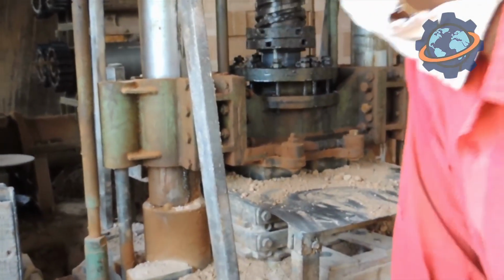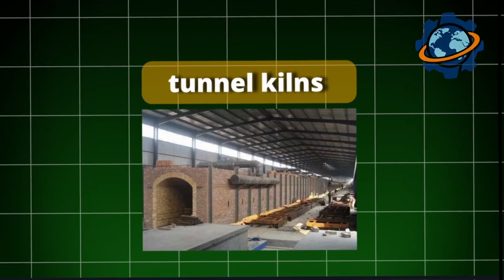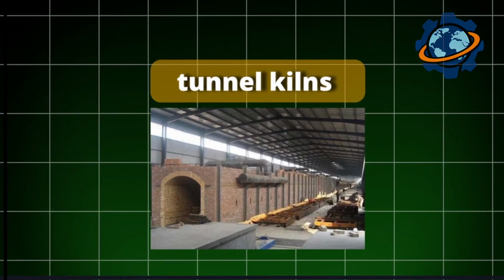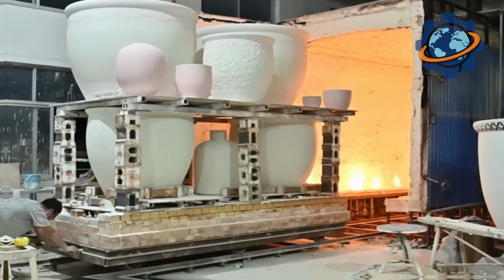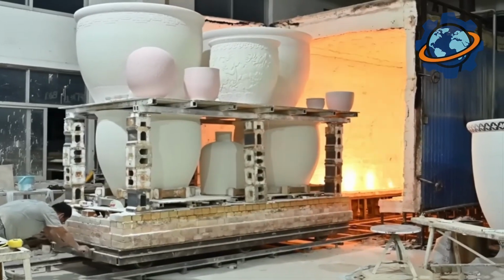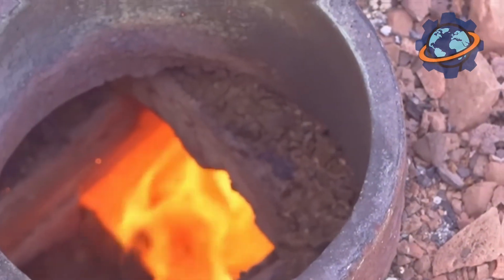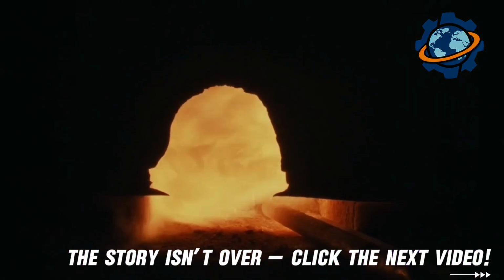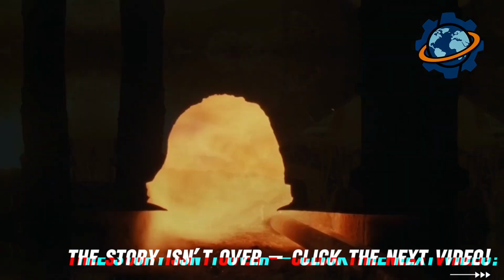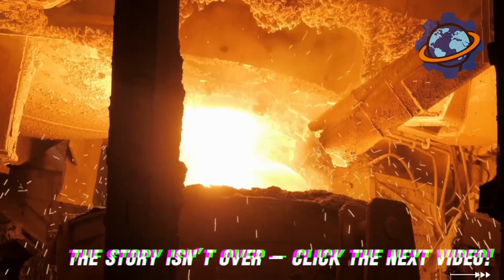The final firing begins. Kiln cars enter tunnel kilns heated to 2,600 degrees. The journey takes 48 hours, crawling through zones of increasing temperature. In the first zone, remaining moisture evaporates. Second zone, raw clay begins sintering, particles fusing at edges. The critical third zone pushes temperatures beyond anything the bricks will face in service.